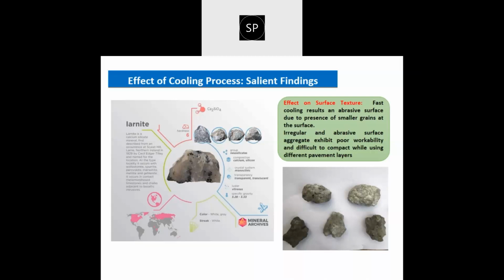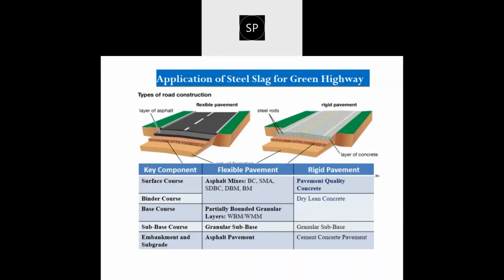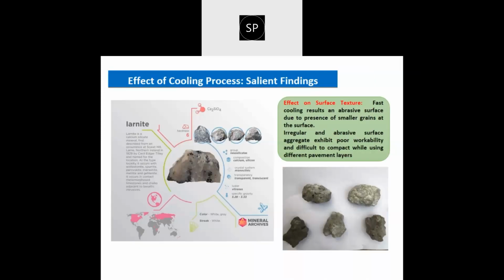So fast cooling results, like if we immediately cool the slag by pouring water or spraying a jet of water on top of it, then it may result in an abrasive surface due to the presence of smaller grains at the surface. Besides that, this process also creates a vesicular structure in the slag, which absorbs binder like bitumen binder and cement when we utilize it as a substitute inside the asphalt concrete or in cement concrete. So this vesicular structure should not be there, and the aggregate produced through the process should be as good as the conventional natural aggregate in terms of surface appearance.